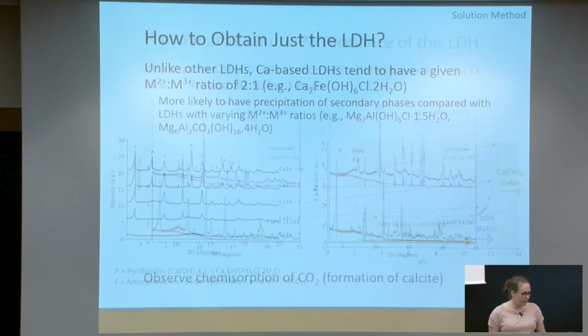So now that we've worked out how to make the phase purity, I should mention why we want to make the phase purity. It's because if you have these secondary phases present, they're going to change your capture behavior. So if you have calcium hydroxide present, then you're going to be forming calcium carbonate, and that needs a temperature of about 900 degrees Celsius to regenerate.